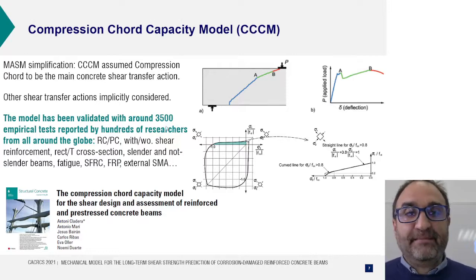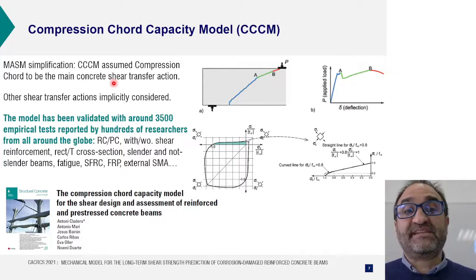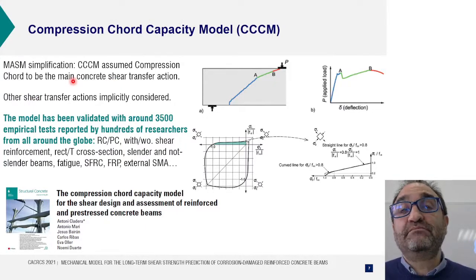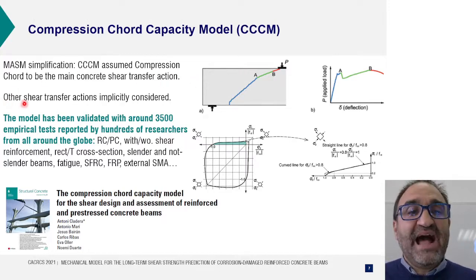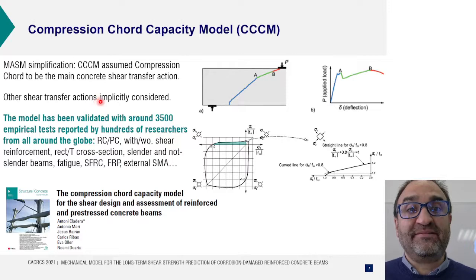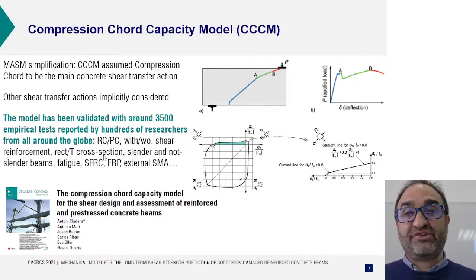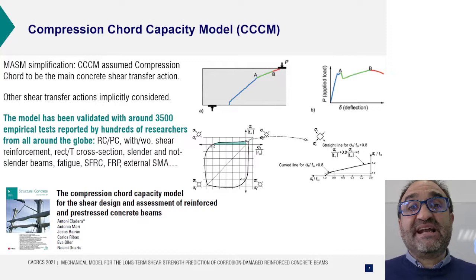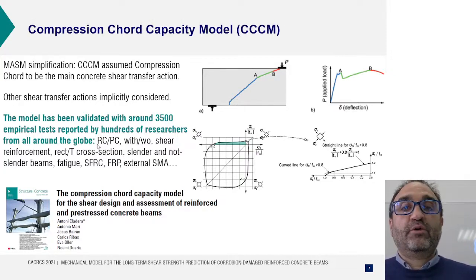The MASM model was simplified into the Compression Chord Capacity Model, which considers that the main contribution of the concrete is through the uncracked concrete in bending, and the other shear transfer actions are implicitly, not explicitly, considered. This model has been validated up to date with around 3,500 empirical tests for reinforced concrete and prestressed concrete beams with and without shear reinforcement, with rectangular or T cross section, for slender and non-slender beams, in cases of fatigue, steel fiber reinforced concrete, beams with internal FRP bars, with external shape memory alloys, in many different situations. So we thought that it was necessary to extend the model for the case of corrosion.